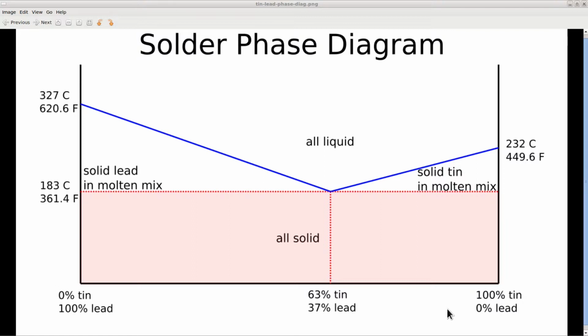But if we move in between the two extremes, where we have a certain percentage of lead and the remaining percentage of tin, the temperature is different, is lower in particular. And with an alloy made of 63% tin and 37% lead, we have what is called the eutectic point, or the point where the melting temperature is the lowest possible. Such temperature is 183 Celsius, or about 361.4 Fahrenheit.